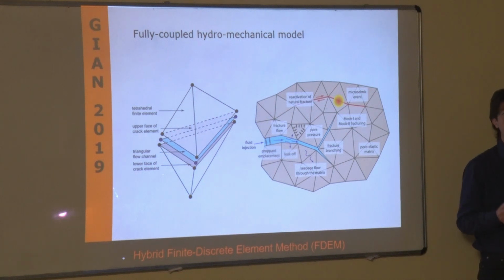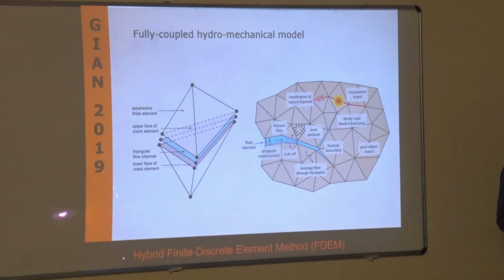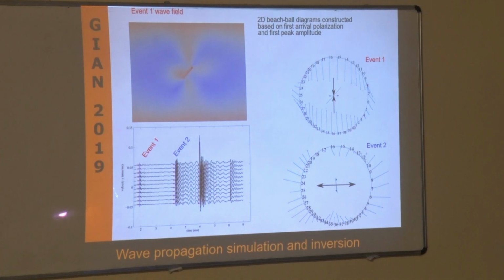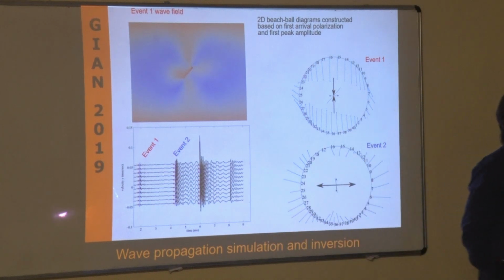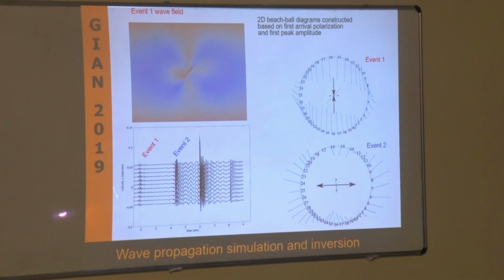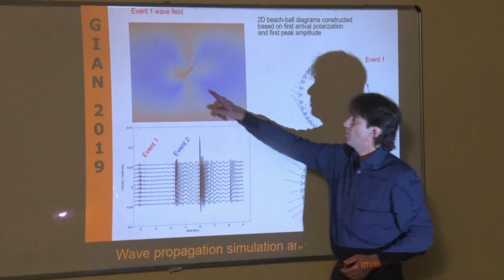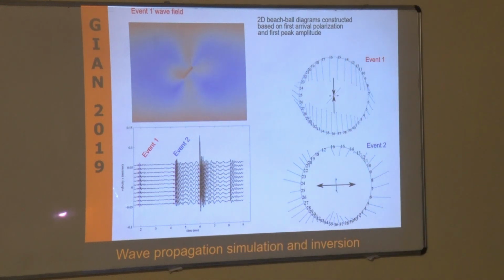In other words, by just propagating a fracture, you are creating a very small seismic wave that will start propagating. And depending on the energy associated with that process, you can go from a very small so-called acoustic emission up to a seismic event. That means that if I have, for example, very small pre-existing fractures, and I compress that system, it tries to break. And generally what you develop are two wing cracks at the tips of your system.